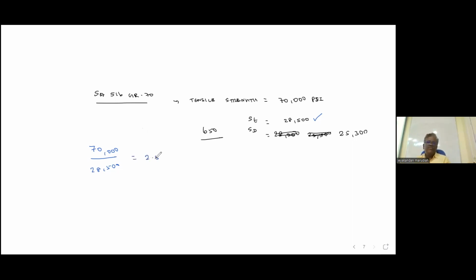So approximately 2.5 times we are giving a reduction. What is the meaning of this? Suppose I have a tank shell of 25 mm actual thickness, but my originally required thickness is only 10 mm. Only 10 mm is required because I am giving a 2.5 times lesser value in the calculation. So my calculated thickness is coming more. You understand this?